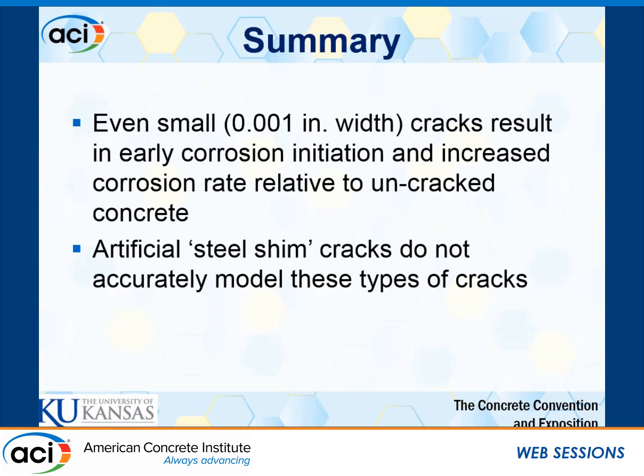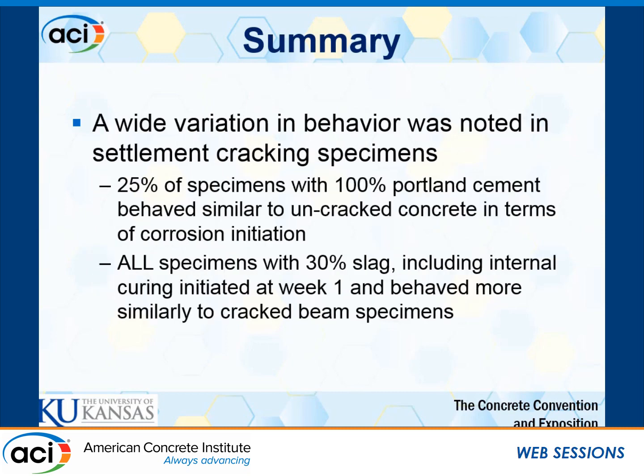So starting to summarize here, we've seen that even with really narrow, even down to 1 mil wide cracks for some of these specimens, we can see early corrosion initiation with our test series. And for this test setup, looking at settlement cracking, we're concluding that the stainless steel shims that we use don't necessarily accurately model these types of cracks. We see a wide range of behavior with our test results. Again, noting that about a quarter of our settlement cracking specimens with 100% Portland cement still had not initiated corrosion over 20 weeks into testing.